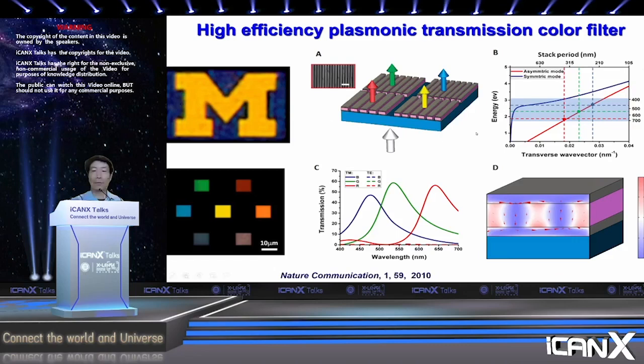This again utilizes a surface electromagnetic wave that's propagating between the metal and dielectric surface, the so-called surface plasmon. And it's using two surface waves. The coupling of those gives rise to hybridized modes, very much like how molecules form bonding and antibonding orbitals. And you can select one of the modes by using this grating structure. You can scatter into them and scatter out. Simply put, that's a filter.